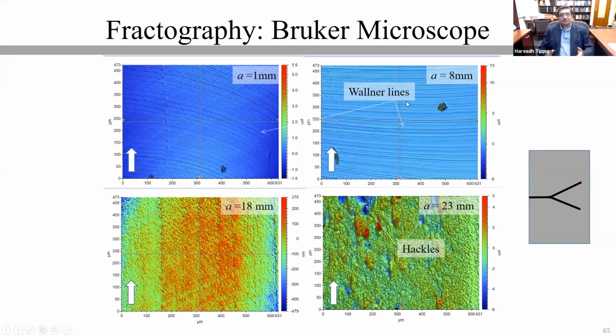Wallner lines are the stress waves that interfere when they reflect off of the free surfaces of the specimen and create these periodic structures. And the bottom, the lower left corner, represents your mist region, where it is a preamble to the Hackle region, where big chunks of material are being pulled out from the substrate. We are able to measure the surface roughness for each of these stages.